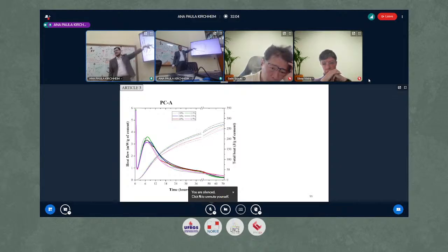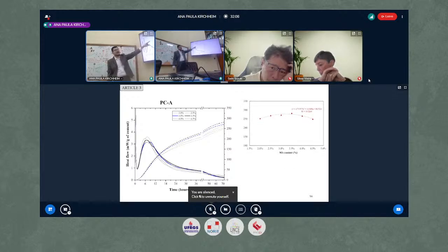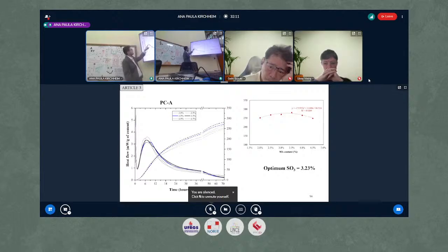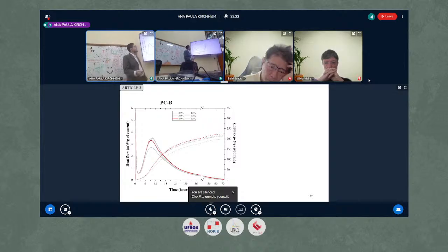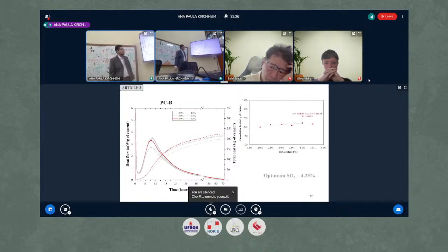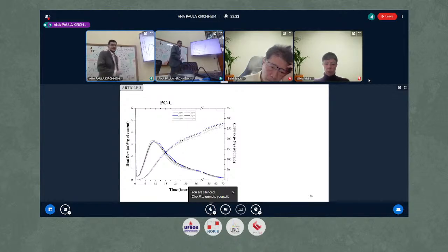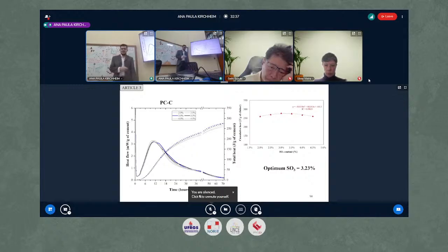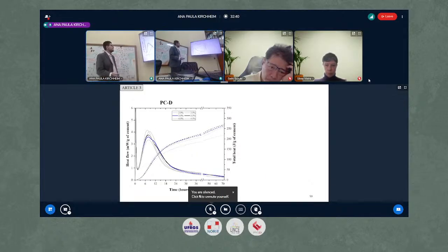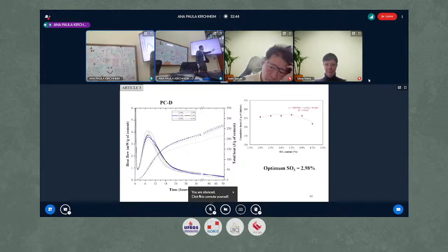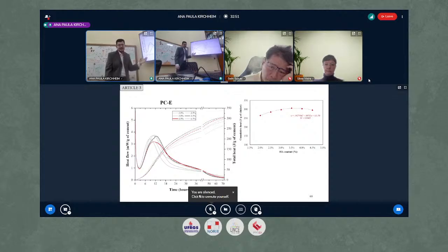So if we analyze the total heat now, we can see that indeed the optimal content will be between 3 and 3.5. In this case, 3.23%. And we did this for the eight clinkers. So PCB, according to heat, will be between 4 and 4.5, and according to the total heat, 4.25%. For PCC it would be between 3 and 3.5, and total heat 3.23%. PCD between 3 and 3.5, and for total heat it's outside the range, at 2.98%. For PCE between 3.5 and 4%, the total heat 3.69%.